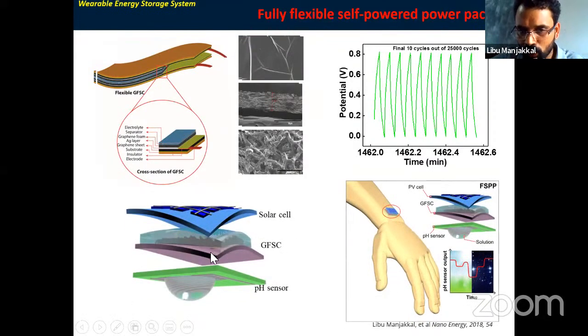Then I integrated this supercapacitor, called a GFSC, graphene foam based supercapacitor, with a pH sensor and a solar cell. The solar cell generates the energy, which is stored in the graphene foam based supercapacitor and used to power the chemiresistor based pH sensor. As you can see here, on the hand we attached these devices, and in the daytime it can charge using the solar cell, store the energy for the night, and continuously power the device. This work was recognized with one of the best UK university category awards, provided with industrial support.